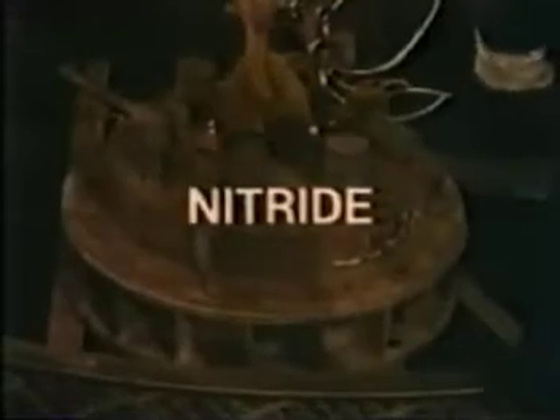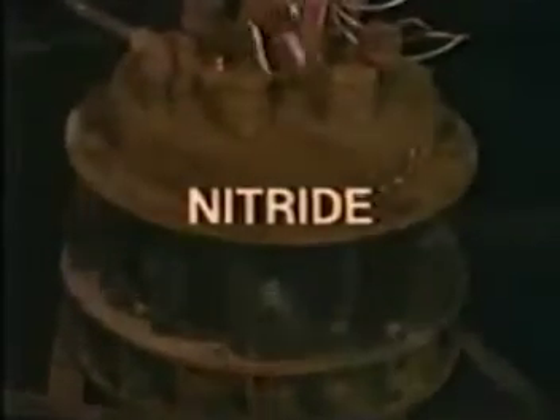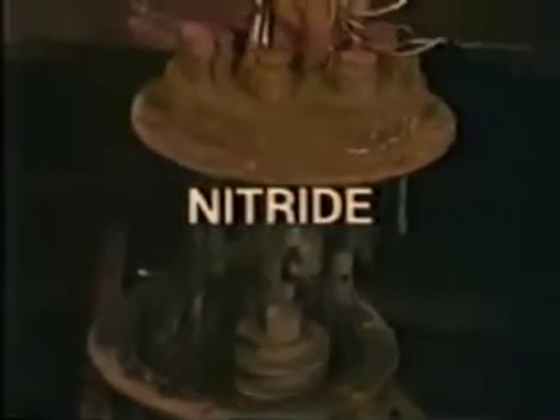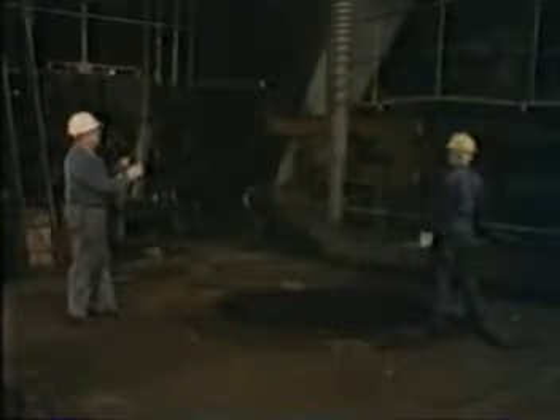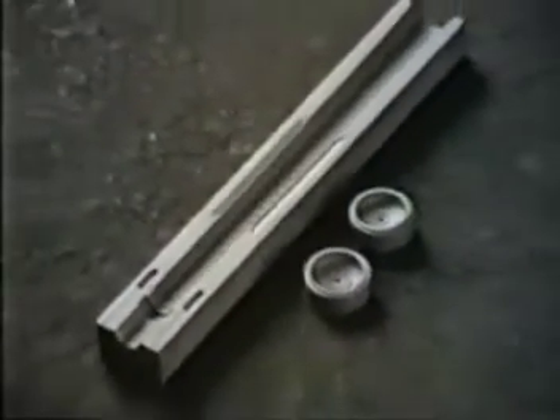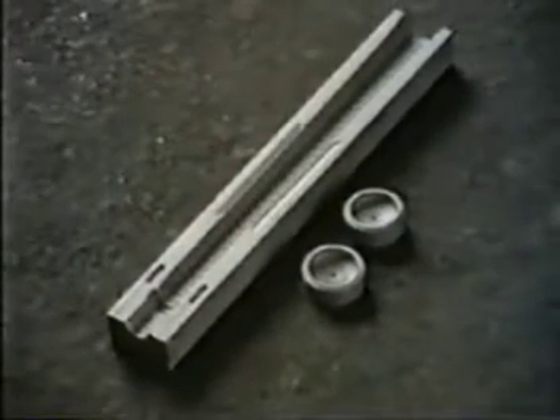Nitriding is another case hardening process that is performed by loading certain alloy steels that are suitable for the nitriding process into an airtight retort that is then heated to about 1,000 degrees Fahrenheit while exposed to an ammonia gas. The heat causes the ammonia to break down into nitrogen and hydrogen. The nitrogen combines with the iron in the steel to form a chemical compound in the outer layer called iron nitride. This layer gives the steel's surface a particularly hard and wear-resistant character.